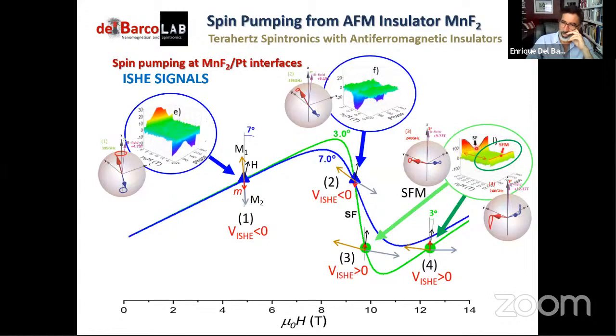Remember I told you there is some background signal. It doesn't really disappear, but it looks to be about the same. So it's most likely coming from the spin Seebeck effect. Once we move across the spin flop transition, we develop an equilibrium magnetization from the canting of the sublattices, and that is going to amplify, make the spin Seebeck effect much more efficient. That is not to be expected at lower fields. You could still have it, but if you just work with k zero modes, in principle, you shouldn't. Okay, sir, that clears my question.